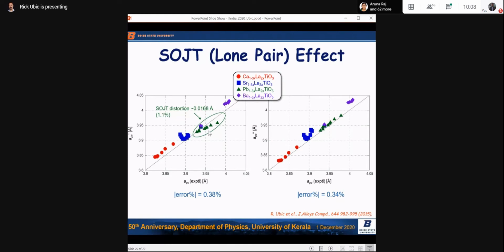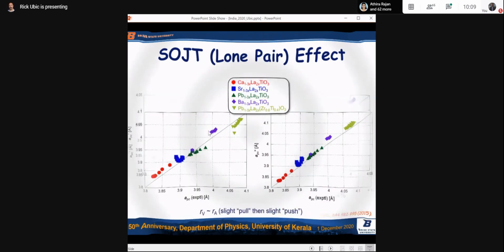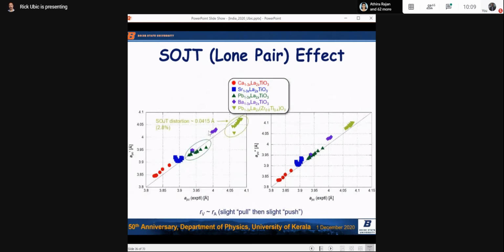And I think that's evidence of the second order Jahn-Teller effect, something called the lone pair effect that lead, everyone knows, has because of the electronic configuration of the lead 2+ cation. And we see the same thing if we include lead lanthanum zirconate titanate, so PLZT. We did some work on this too.